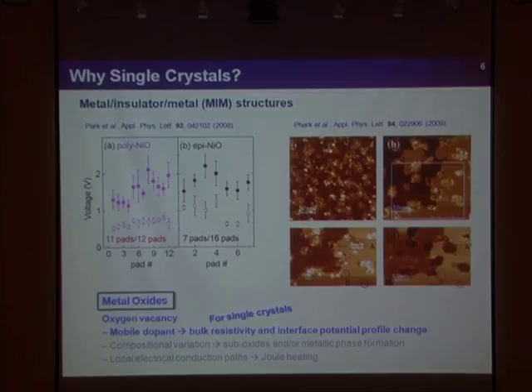Around 2005, I started research on RRAM using thin film metal-insulator-metal structures. At that time, Samsung was extensively working on nickel oxide thin films, so I chose nickel oxide. I compared two different films with identical structure, platinum-nickel oxide-platinum: the left-side polycrystalline thin film and the right-side epitaxial thin film. You can see there's a big difference. In the epitaxial thin film, the switching yield is quite low, less than 50%, but in the polycrystalline film, all of them show very stable switching.